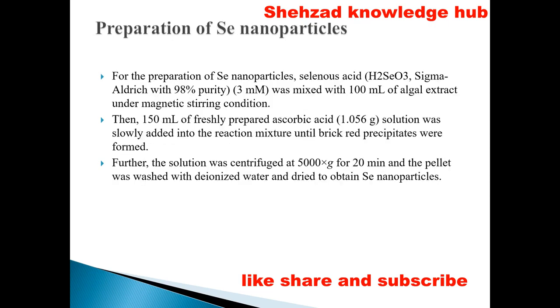Preparation of selenium nanoparticles. For the preparation of selenium nanoparticles, selenious acid was mixed with 100 milliliters of algal extract under magnetic stirring, then 150 milliliters of freshly prepared 1.056 gram ascorbic acid solution was slowly added into the reaction mixture until brick red precipitates were formed. Further, the solution was centrifuged at 5000 g for 20 minutes and the pellet was washed with deionized water and dried to obtain selenium nanoparticles.